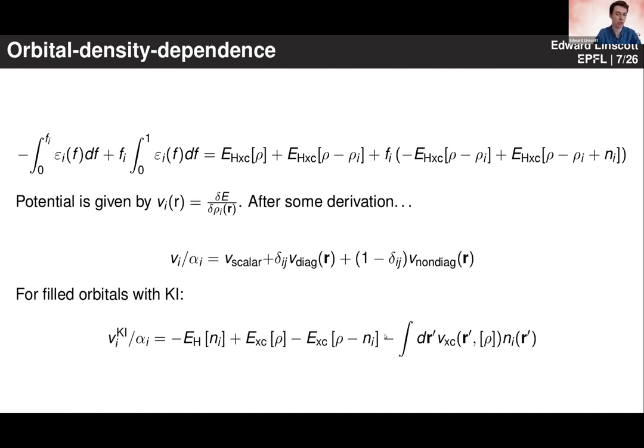So for our empty orbitals, these spatially dependent potentials are non-vanishing. But often what you will see at the first level of approximation, if you just focus on the occupied bands, is that this potential will shift blocks of bands up and down, which is what we want to do, because we know that PBE, or DFT more generally, gives bad band gaps, for instance.